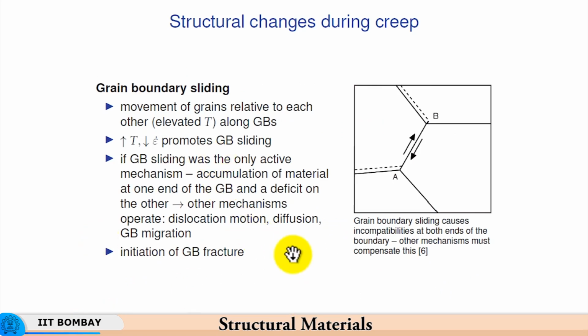We have seen that the structural changes during creep include another phenomenon called grain boundary sliding, where there is shear across the grain boundaries, and this grain gets displaced with regard to the other. So, here you have created a deficiency of material, you have excess of material, and this is compensated by other mechanisms like diffusion, for example.